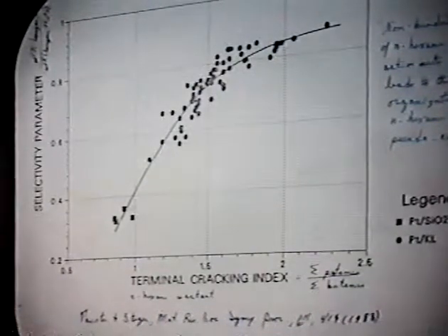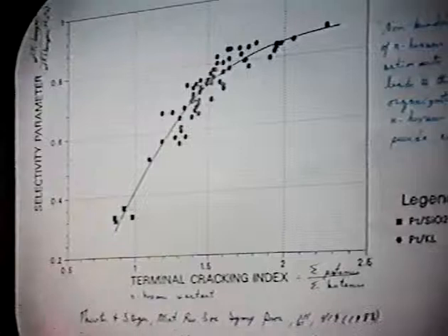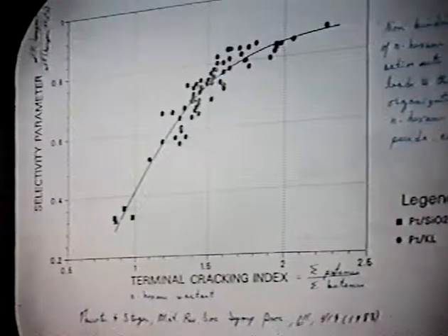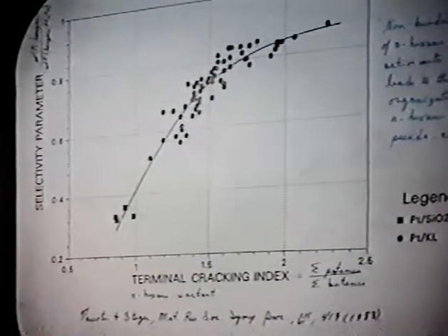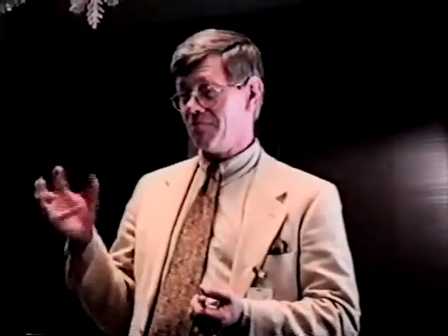The idea that they had was that normal hexane goes down these parallel channels and has a preferential end-on collision with the platinum, and then you get 1-6 ring closure. Now the problem with that is if you look at normal hexane and its conformers, it can easily ball up and just move down the channel any way it wants. There's no reason why it should hit end-on. And so that doesn't look very convincing.